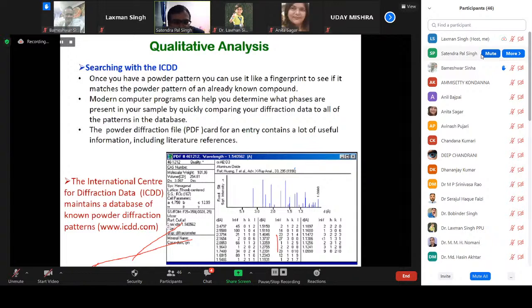Now, once we get the XRD pattern, in order to analyze it, the first thing we do is match the XRD pattern with the existing databases. There is the ICDD, the International Centre for Diffraction Data. They have more than 2 lakh files, the powder diffraction files, where you can match your XRD pattern with the given XRD patterns. From there, you can get a lot of information, including the lattice parameter, the crystal systems, and sometimes the references. So the best way to analyze any XRD pattern is to go for qualitative analysis using the known crystal systems and the ICDD software, and match your XRD pattern to get the information.